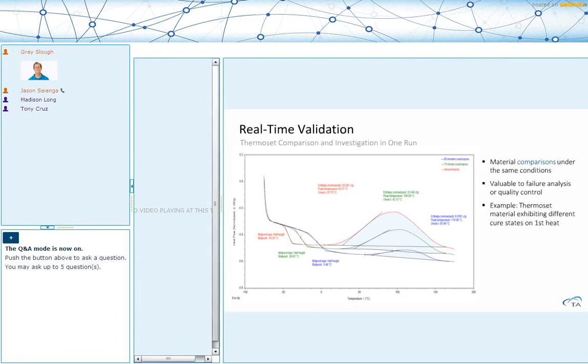Real-time validation. We can certainly say in this example, we're looking at some cross-linking materials. It's epoxy materials. In this case, it's uncured versus 15 minutes versus 60 minutes. This experiment allows us, the X3 allows us to take each of those materials at time zero and run them all at the same time. So there's no question about whether those materials cured while waiting to be tested on the DSC, whether there was some cross-linking taking place, whether there was some material change as we waited to make that measurement.